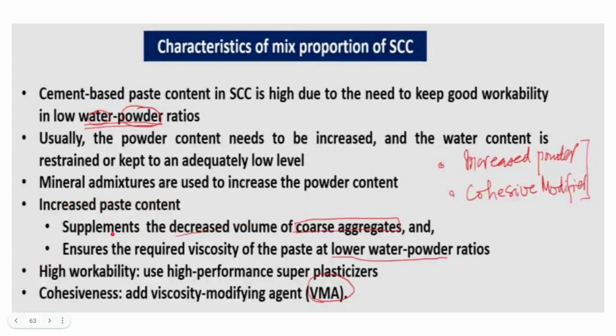So increased paste content supplements the decreased volume of coarse aggregates, as I just mentioned, and ensures the required viscosity of the paste at lower water powder ratios. So both of them are satisfied by increasing paste content: decreased volume of coarse aggregate and required viscosity of the paste. Then high workability: for high workability, as I discussed, we have to use high performance super plasticizers, and for cohesiveness we have to add viscosity modifying agent or VMA.